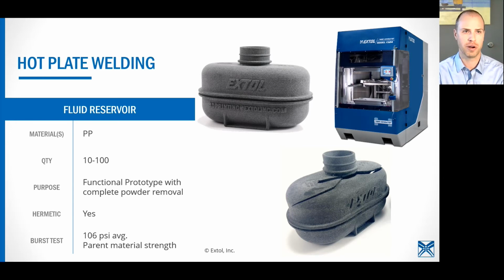So here's an example of a part that's been burst. Again, these are printed in MJF polypropylene, hot plate welded, then burst tested, which is a common testing method for this type of part. One thing we always want to see with hot plate welding is that we're breaking away from the weld, and breaking at the parent material, because we know that then the weld is as strong as we can get it. If we need to make the parent material stronger, we need to go back and tweak the part design. But the weld's as good as we can get it.